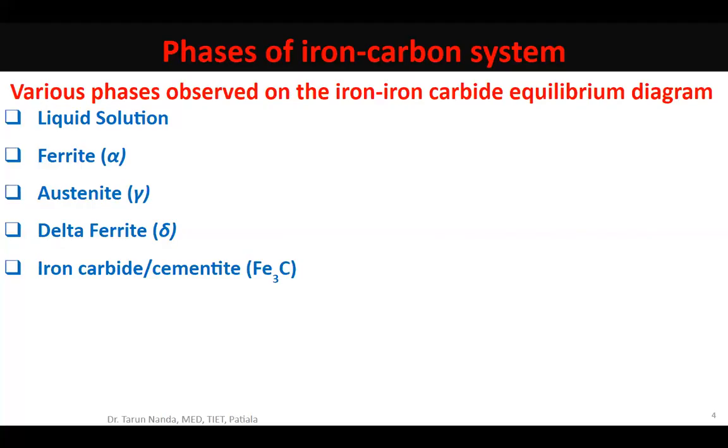It's slightly magnetic below 210. So the Curie temperature of the cementite phase is 210 degrees centigrade, and you will find a dotted line to signify this information. So cementite is partially magnetic below 210 degrees centigrade, and if the iron carbon alloy containing it is at a temperature higher than 210, then cementite becomes totally non-magnetic. The melting point of cementite is also very high, 1227 degrees centigrade.